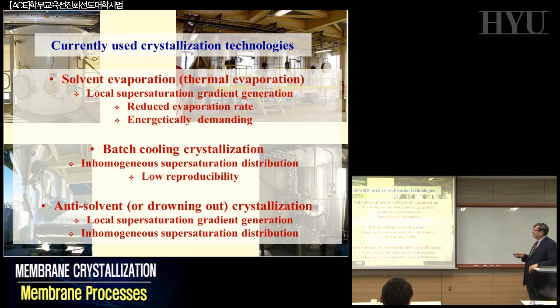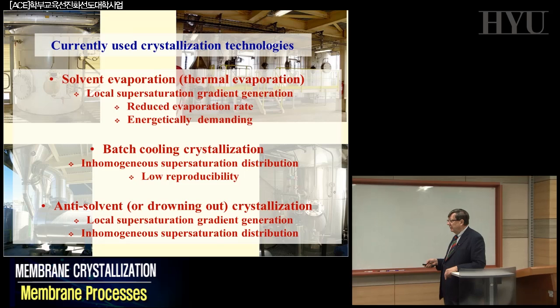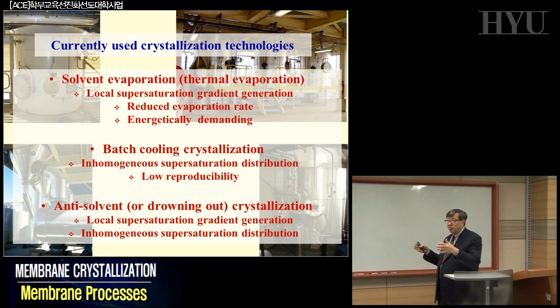There are some other ways to crystallize. An interesting way is this anti-solvent or drawing out crystallization. That means you can remove the solvent in a different way, or you can introduce some other species which are not solvent for the chemicals which were dissolved in solvent number one, in water. So if you start to introduce a solvent which is not a solvent for the species, you can have an anti-solvent or drawing out crystallization. Keep in mind that in this case, thermal evaporation and today also anti-solvent are the ways where membranes are going to play a quite interesting role.